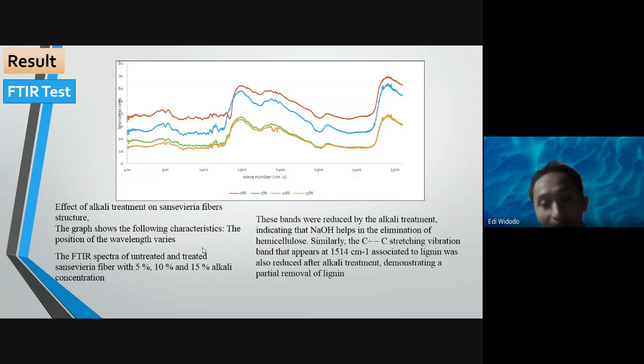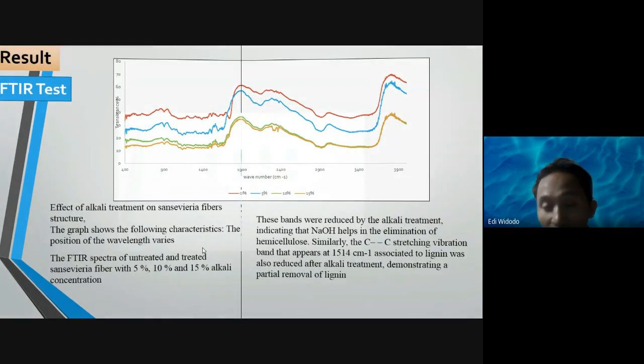These bands were reduced by the alkali treatment, indicating that NaOH helps in the elimination of hemicellulose. Similarly, the stretching vibration band that appears at 1514 cm-1, associated with lignin, was also reduced after alkali treatment, demonstrating a partial removal of lignin.